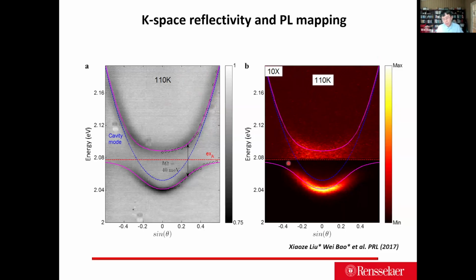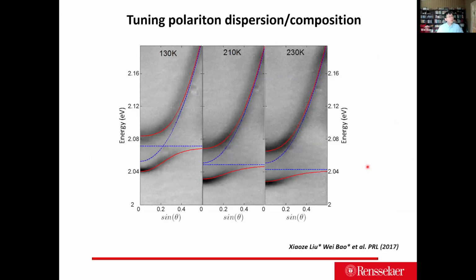This is the photoluminescence. At that time, almost eight years ago, this sample looked really promising at first glance. We also tried to tune the temperature. The exciton does tune with the temperature while the photon cavity line remains constant, and we can achieve different hybridizing ratios in the lower polariton, so that it has a certain portion of the exciton component and a certain portion of the photon component. We can tune them at will.